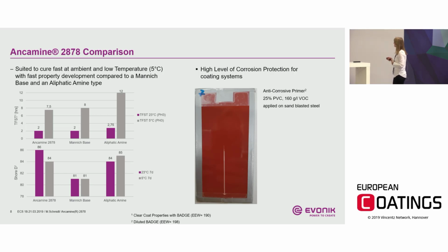On this product, we tested in a salt spray and Prohesion test. There we came to the conclusion that it has a relatively high corrosion protection in an anti-corrosive primer formulation. It's applied on sandblasted steel, the standard. But for the primer, we do not have only the standard liquid epoxy resin. We also have the diluted version tested, seen here below.